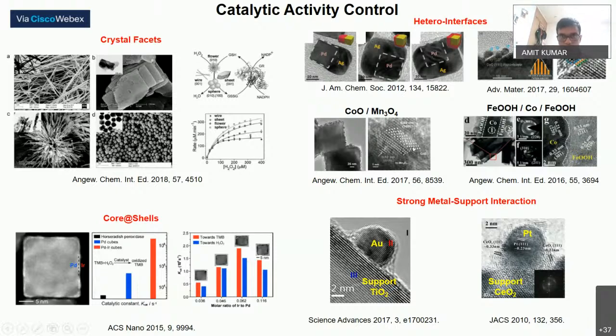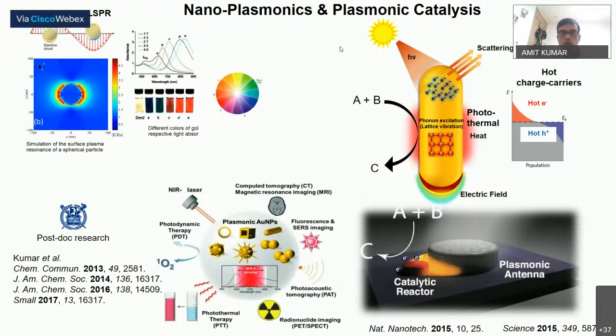in the heterogeneous state. Another interesting feature of nanoparticles is that you can get additional physical properties, for example, optical properties. Nanoparticles of gold and silver have a unique ability to absorb light, and their light absorption capability can be well tuned as you change their sizes, shapes, and morphologies. During my postdoctoral research at Seoul National University, I received extensive training in controlling their sizes and shapes by various solution-based methods, and found that controlling these structures at the few-nanometer scale is very crucial for tuning their plasmonic properties. When light is incident on these nanoparticles, there are basically three effects which dominate.